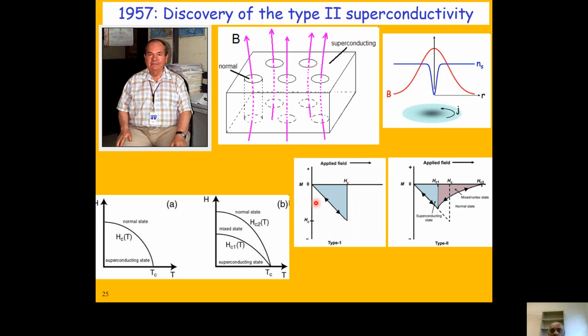If you look at the magnetization, for a normal type 1 superconductor, if everything is superconducting, your M goes like minus H, that's total perfect diamagnetism. But if you have this kind of type 2 or mixed state, it doesn't go back like this one, it shows different behavior. Rather than becoming zero here like at HC for type 1 superconductor, that's the critical field, type 2 superconductors don't become zero, they maximize at this point, then go to zero at this point.